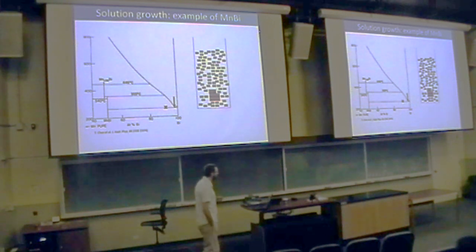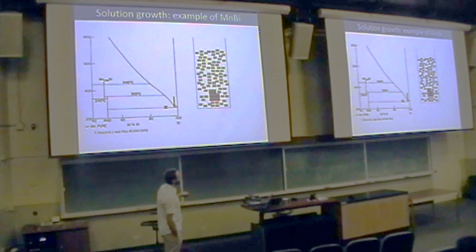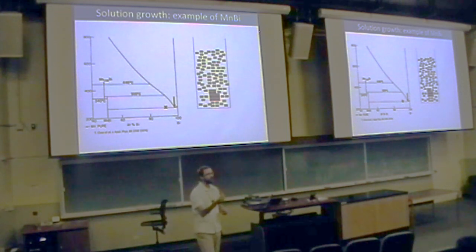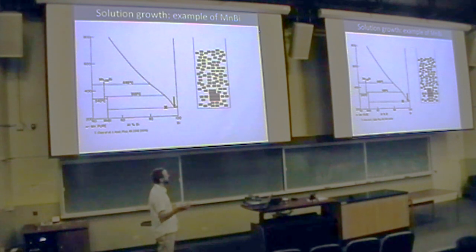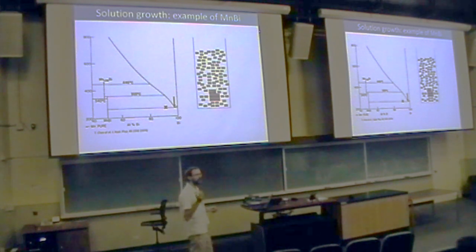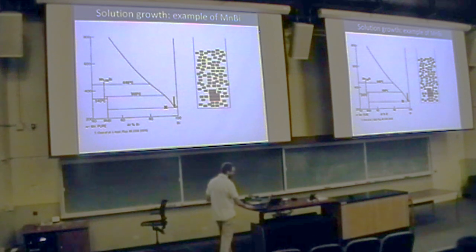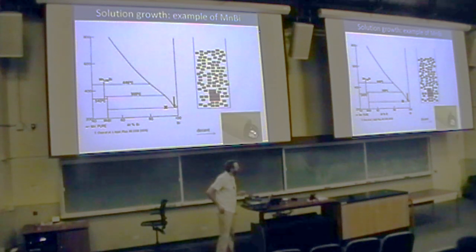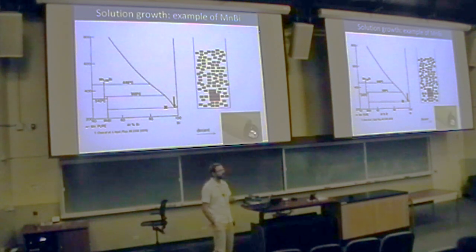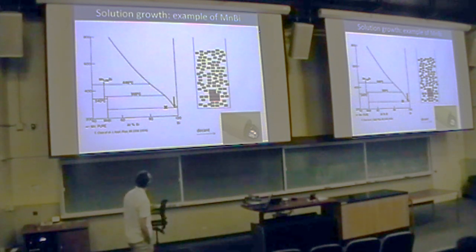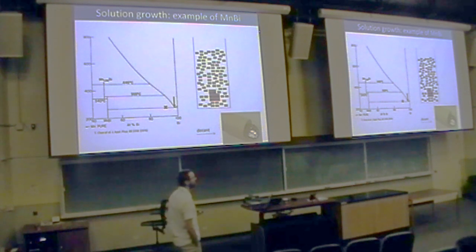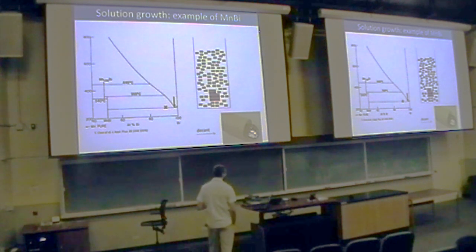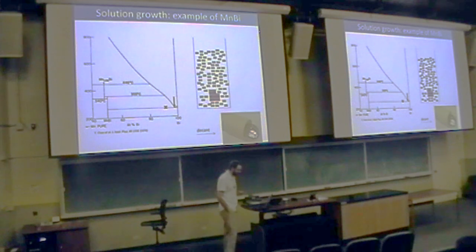Okay? So then, just before we reach this eutectic point here, if we keep cooling down below the eutectic point, everything freezes. But just before it freezes, we can remove the excess liquid, and then we have just a nice and shiny single crystal. Okay? So that is how you would use the basic principle for what we call solution growth technique to get single crystals of manganese bismuth.